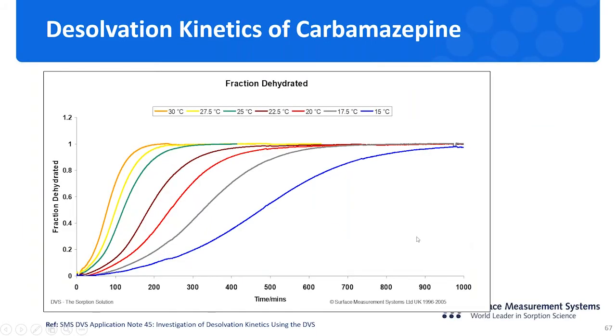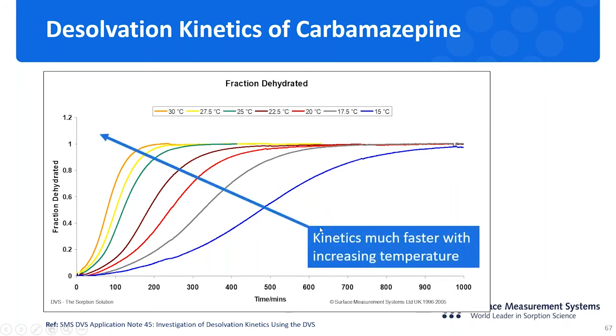So here we have the plot of different temperatures, showing the fraction of the dehydration or desolvation that is happening as a function of time. So what we notice is that the lower temperature, which is 15 degrees here, is much slower compared to 30 degrees here. So at 30 degrees, the dehydration finishes within 200 minutes, but at 15 degrees, it will take about 1,000 minutes. So with the increasing temperature, the dehydration kinetics of this carbamazepine becomes much faster.